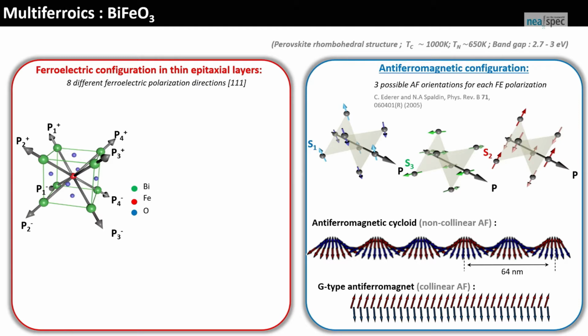temperature. Regarding the ferroelectric configuration, it is a perovskite type of structure, but then the ferroelectric polarization can lie along one of each 1-1-1 direction in the pseudo-cubic lattice. And for each of these polarizations, you can have 3 possible orders for the spins. Then, depending on the strain, you can have either this kind of fancy antiferromagnetic cycloid or a standard G-type